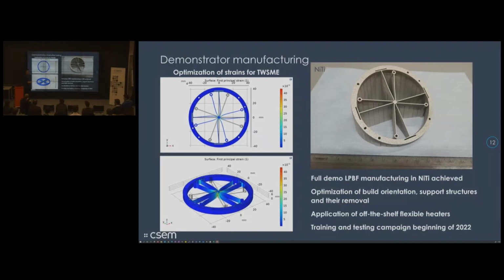Do you see any anisotropy in printed structures, so that mechanical properties depend on how your structure was built, and you see influences from the layers or something like that? In laser powder bed fusion, in as-built material, this is absolutely possible. We haven't done characterization at this stage for that, but after the printing it's possible to do solution annealing, and this usually resets these kinds of effects. So when anisotropy is an issue, solution annealing is one of the ways to reset the microstructure so it's not anisotropic.